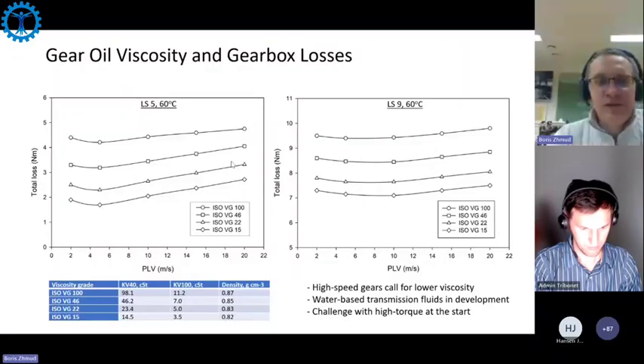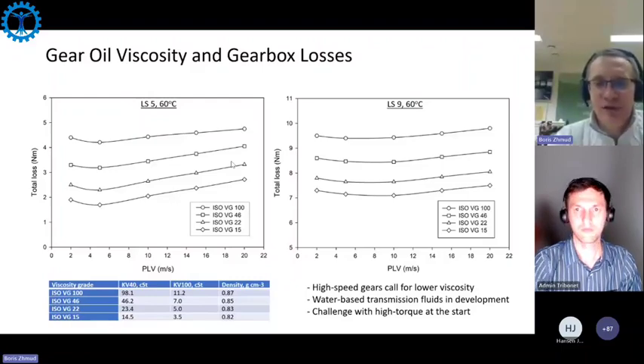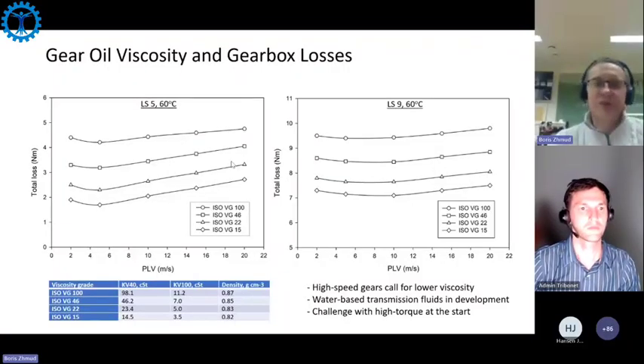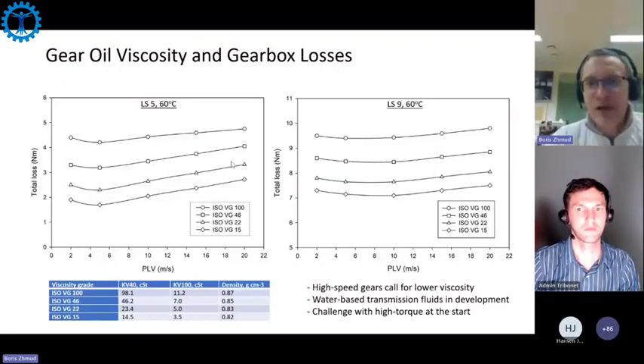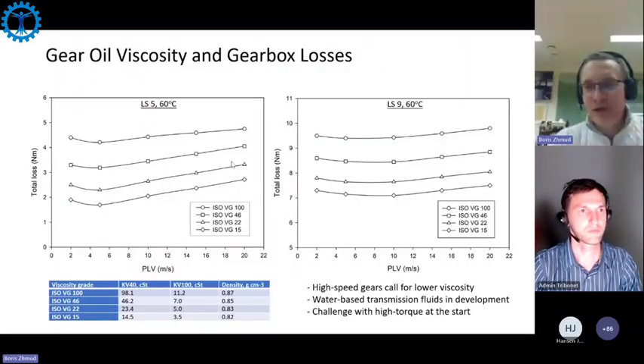And you will see that with fully synthetic lubricant and lower viscosity, you get lower total losses in the FZG test. And you would also expect that you will get, of course, lower losses in your actual transmissions. And you get a consistent effect at lower load stage 5 and at higher load stage 9 in this particular case. You will see that lower viscosity means lower losses, which is good and which also justifies the reason to go moving toward lower viscosity fluids.